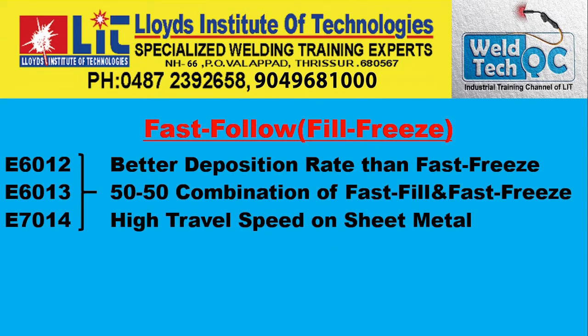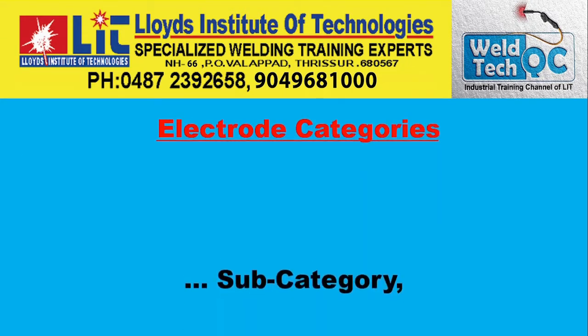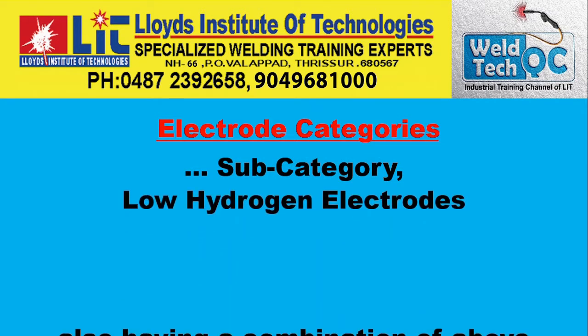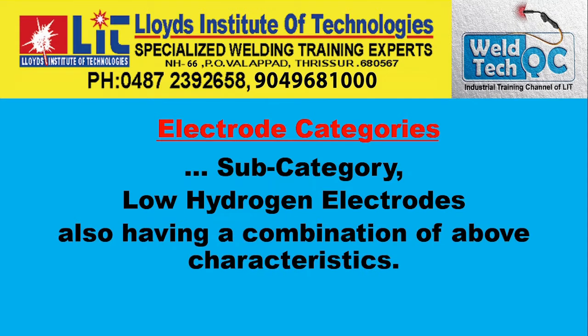The third, okay, next category is low hydrogen electrodes. A subcategory, you can say. This will have both the characteristics of the fast fill as well as fast freeze. While we talk about low hydrogen electrodes, immediately the thing that comes to mind is that this electrode is known as a code electrode, meaning for high quality welding, like X-ray quality welding. Everywhere these are the preferred electrodes. The low hydrogen electrodes are the preferred electrodes, especially E7018.